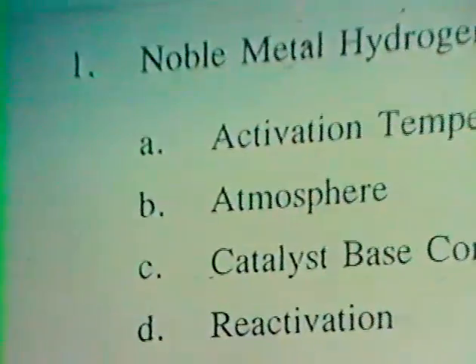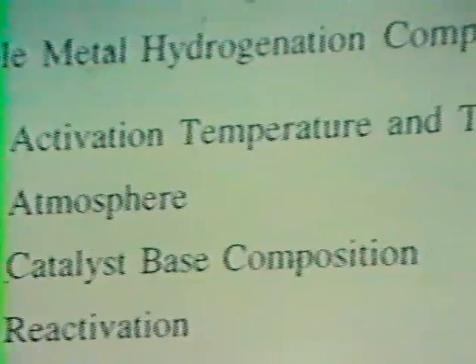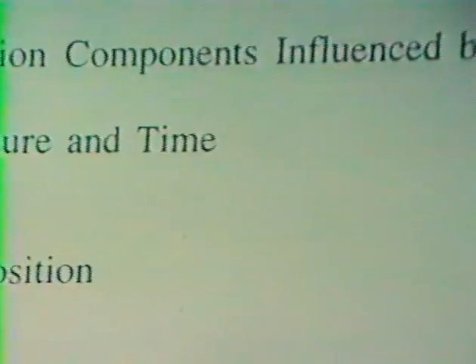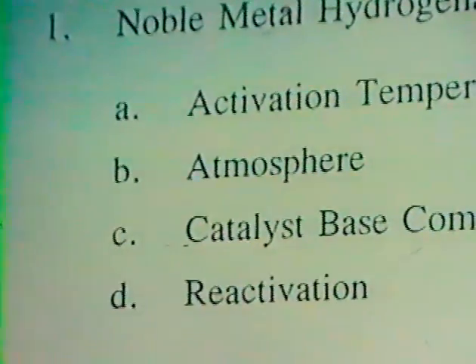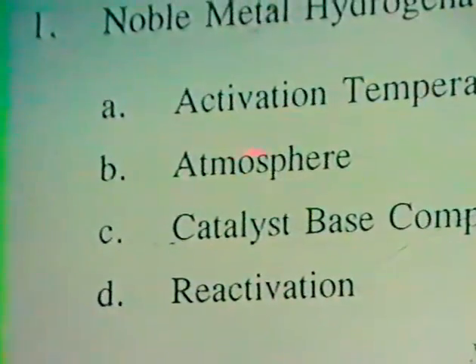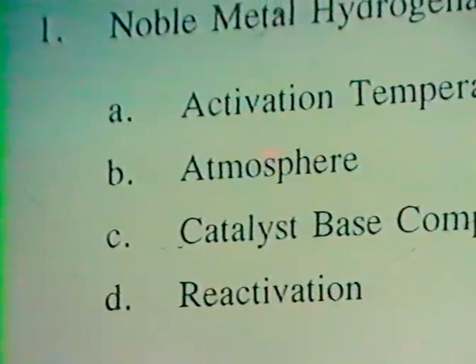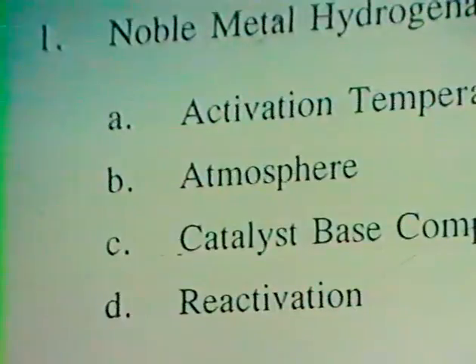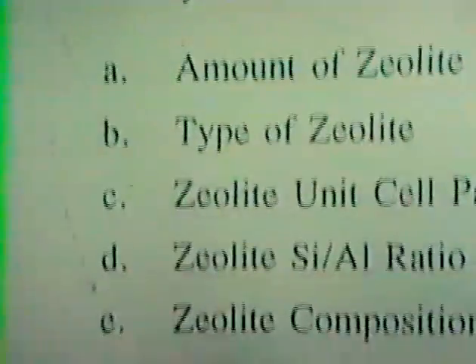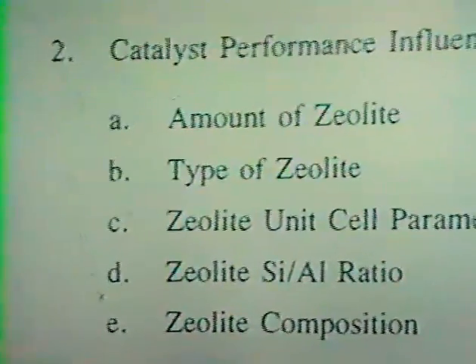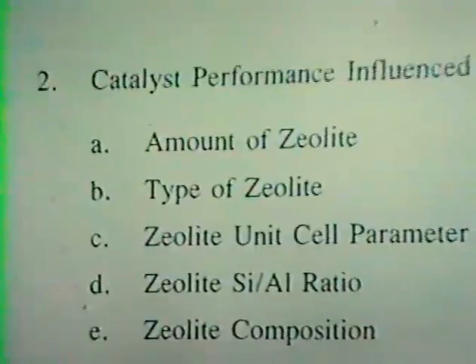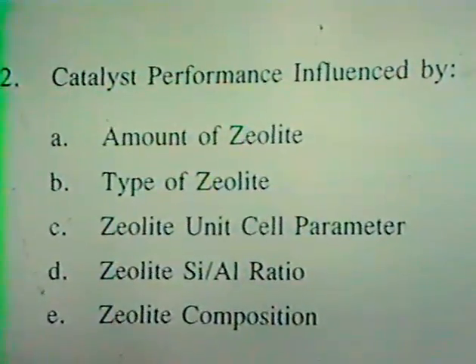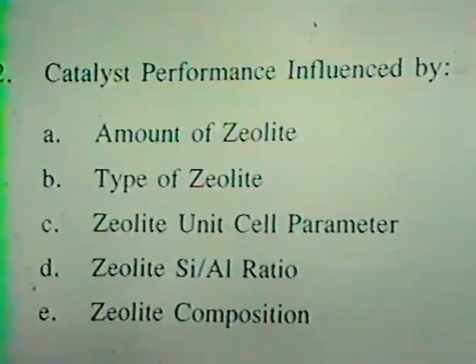The hydrogenation components of these dual functional catalysts, the activation time and temperature are important in obtaining maximum activity. The atmosphere in which they're treated after preparation, whether they're directly reduced or treated with nitrogen or other gases, is also important. The catalyst base composition is important, whether they have rare earth or magnesium or some other multivalent cation to stabilize the structure. One can reactivate these catalysts after deactivation by treatment with ammonia and ammonium ions.